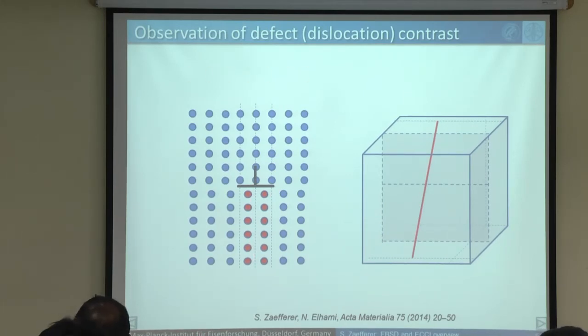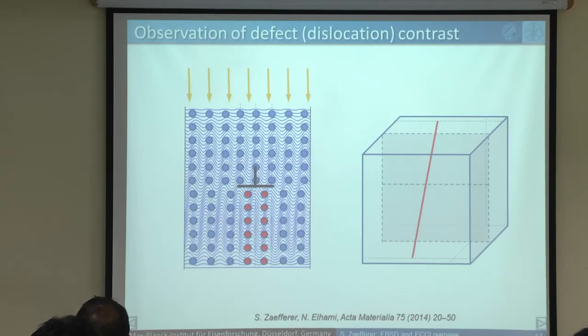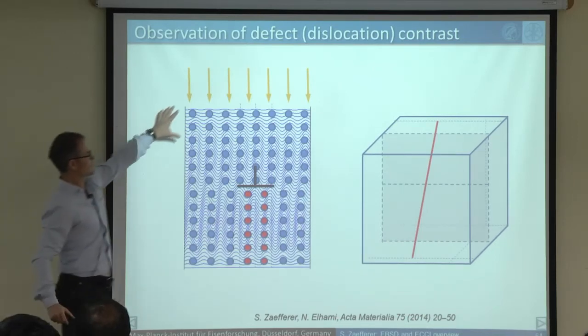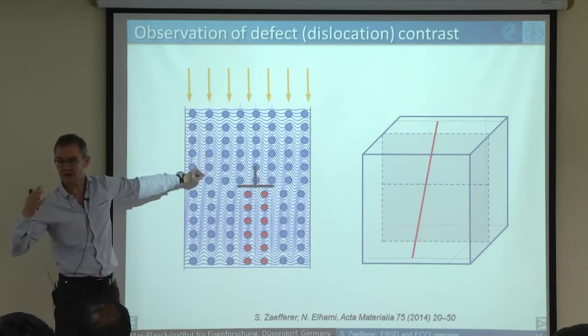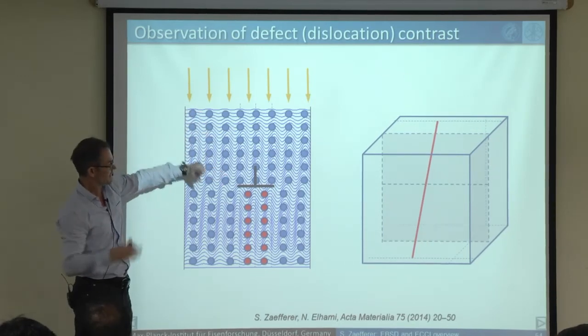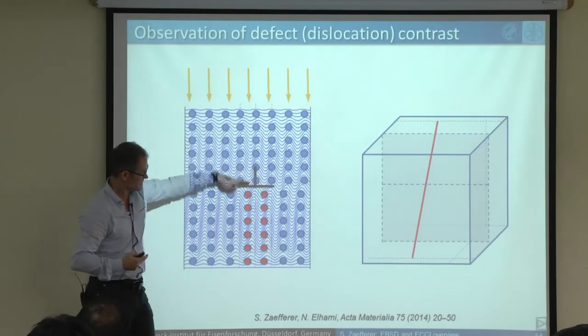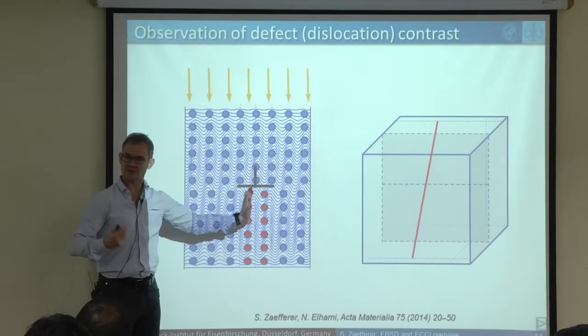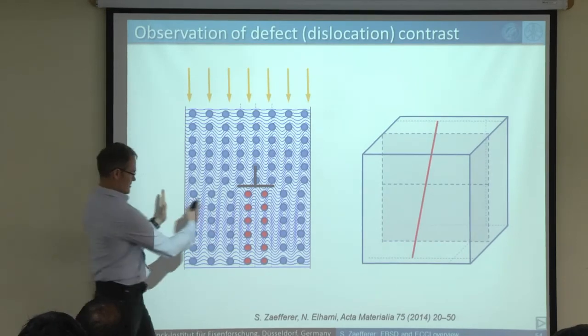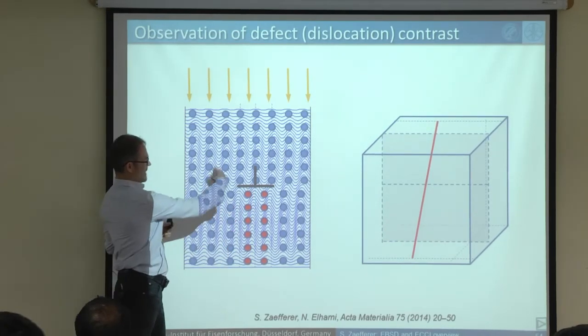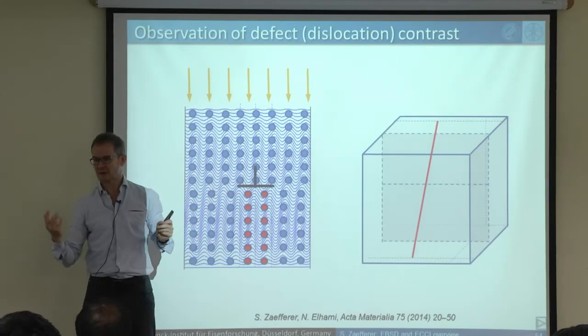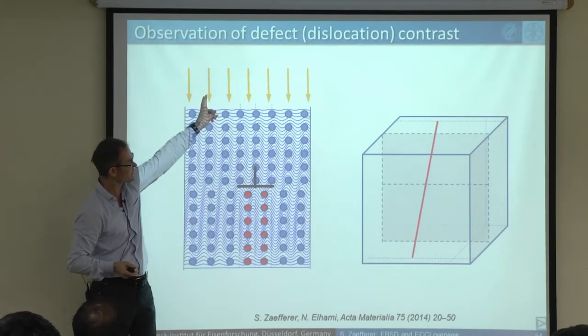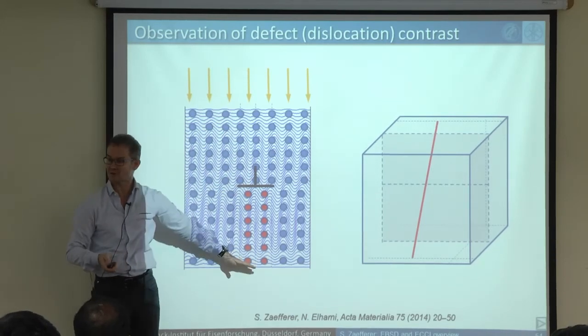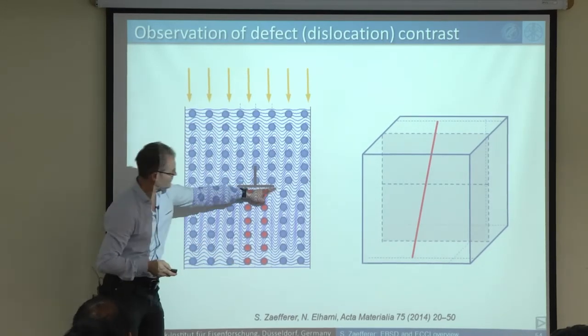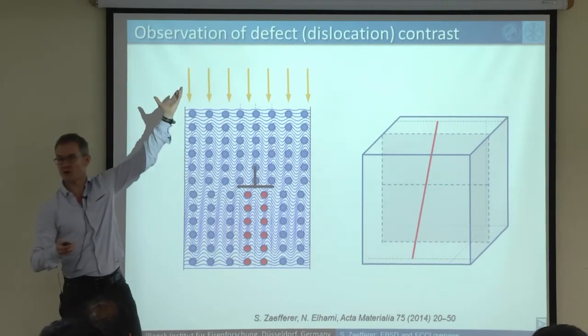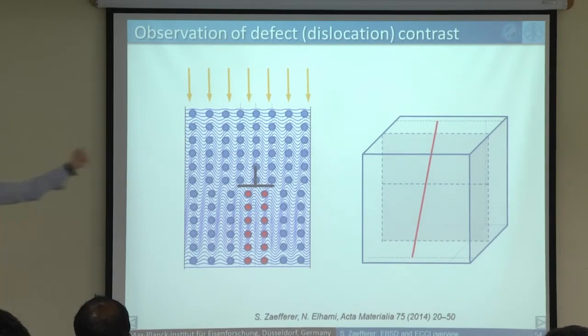So now we put our electron beam on, and we select it such that it will be in channeling conditions, so in Bragg diffraction condition for the perfect crystal. And what happens now when we come to the dislocation? Here, there is one lattice plane missing, so it's no longer in Bragg condition. The waves here are actually shifted by half a lattice plane, and instead of having perfect channeling, they suddenly have perfect backscattering. So as a result, we will see this area as a strong white signal on an otherwise black background.